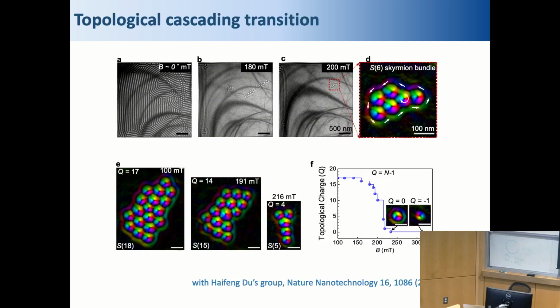Yeah, I would say that it depends on many details. Basically, in the energy landscape, there is a barrier. And the stability of the skyrmion obeys the Arrhenius law. And this barrier will depend on many things. It just depends on details. So is it correct to say that over there you do have a Zeeman scale that's roughly 0.2 Tesla, 200 millitesla? That's where most of them collapse, and that's the characteristic of the barrier that you were mentioning. I would not say that. Yeah, I would not say that.